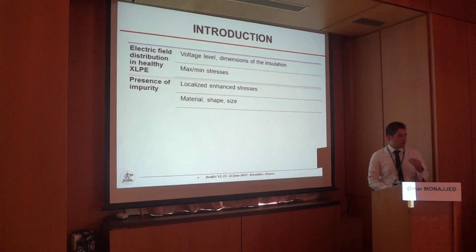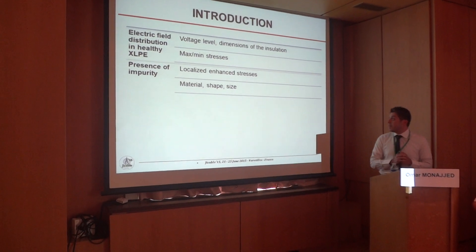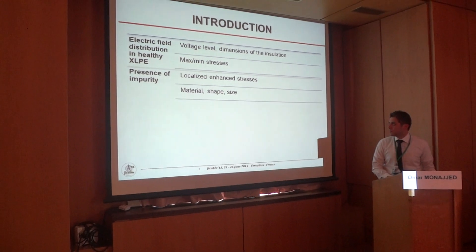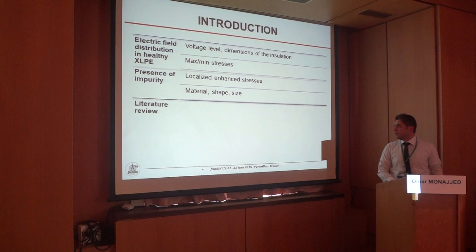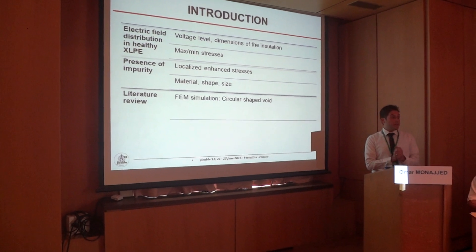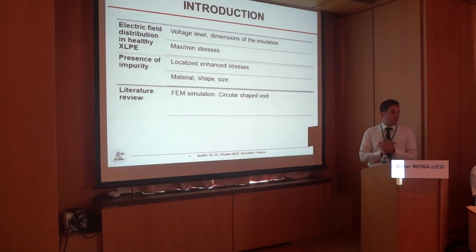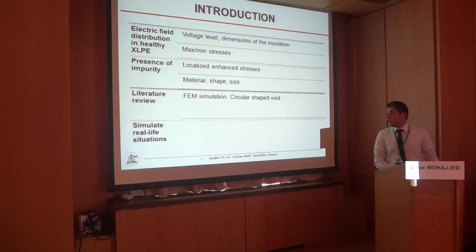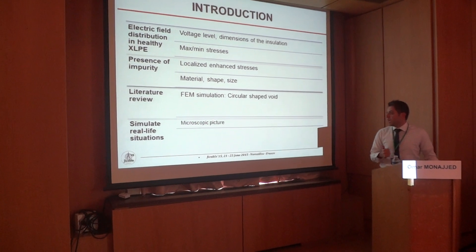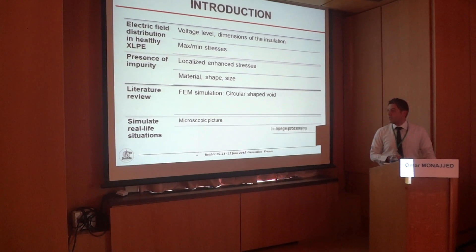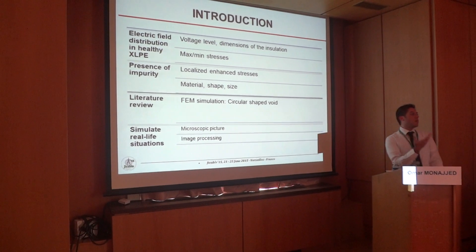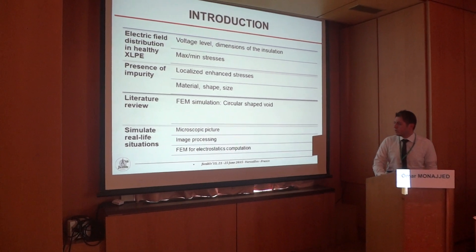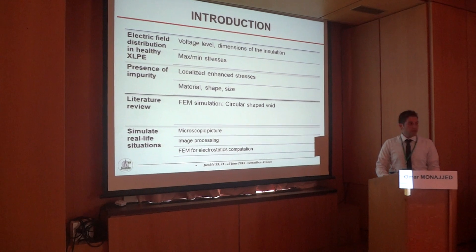Impurities having sharp edges tend to have higher stresses. Also, it will depend on the size of impurities, so impurities having large sizes tend to have higher stresses. In the literature review, they have only simulated using FEM the effect of a circular-shaped impurity, which is not our case. To simulate real-life situations, first we have to take a microscopic photo of the impurity, second we have to perform image processing to determine the boundaries, and third we will calculate the stresses using FEM.